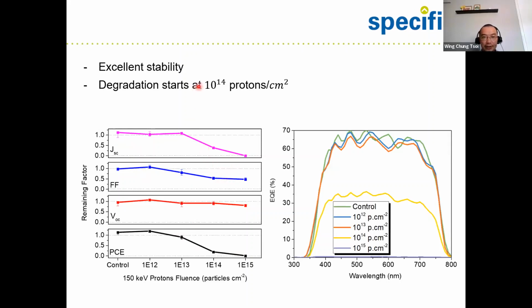So the degradation starts at about 10 to the power 14 protons per centimeter square, but it's already excellent stability against protons at this energy, because a gallium arsenide solar cell, for example, can already degrade quite a lot even at 10 to the power 12 protons per centimeter square. So it's pretty exciting, this result.